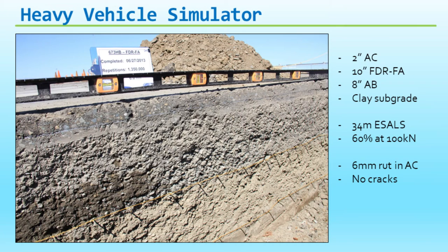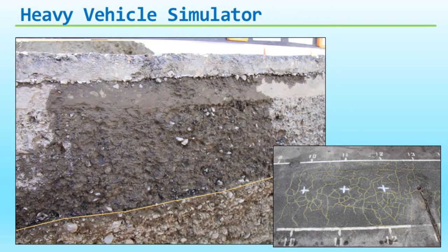At the end of all of that, we wanted to carry on, but we couldn't because we were running out of money. We had 6 millimeters of rut, and that was completely confined in the asphalt. There was nothing in the layer over there. So again, I'm going to use this side over here. That's the cut underneath the asphalt, this is just a saw cut here. That's the foamed asphalt there, and that's the asphalt base underneath, and you can see the clay underneath that.